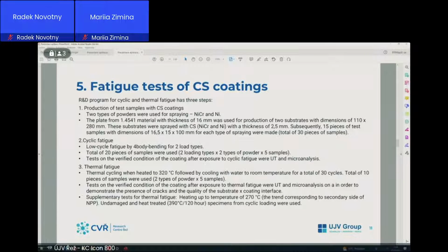After applying fatigue, we performed UT, non-destructive testing, and microanalysis. As concerns thermal fatigue, the first type was drastic. We heated samples up to 320 degrees centigrade, followed by cooling with water to room temperature. We tried to perform 30 cycles.